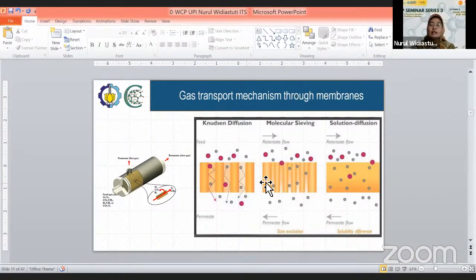And the next one is molecular sieving. In molecular sieving, the key to the selectivity of the membranes is really based on the size of the pores of the membranes, or the material that we use for the membranes. And the pores of the membranes are key, based on the size of the gas molecules that will be separated. So if we want to separate a gas, we can design the pore size of the membranes based on the size of the gas. The gas molecules smaller than the pore size of the membranes will go through the membrane, while the gas with bigger molecular size will be rejected on the surface of the membranes.